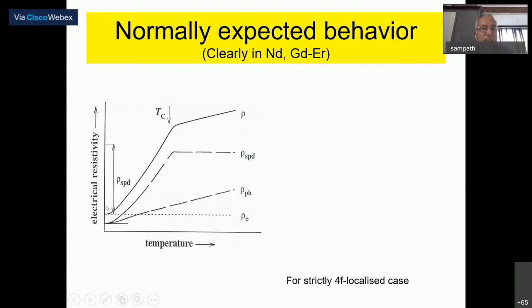One is the residual resistivity, then the phonon background, whose coefficient with temperature is positive, and then a spin disorder contribution in the paramagnetic state, which is supposed to be constant in the paramagnetic state. At the magnetic ordering, you are losing it, because the spin disorder contribution drops at the magnetic ordering temperature. If you add up these three, this is what you get here. So these are normal behavior.